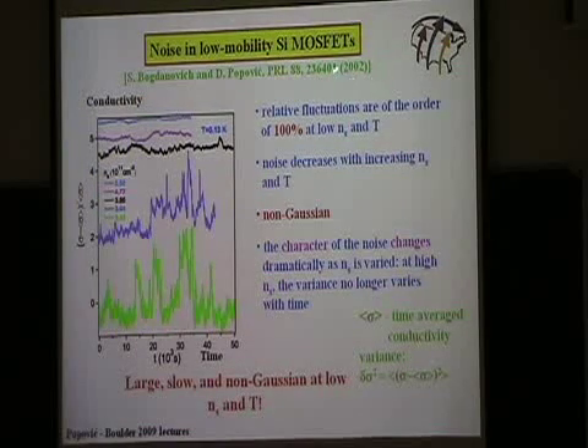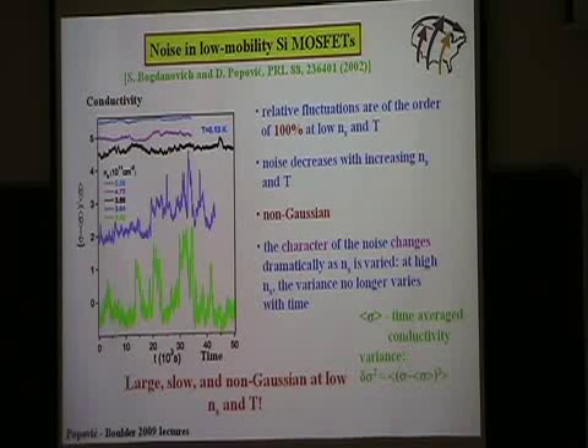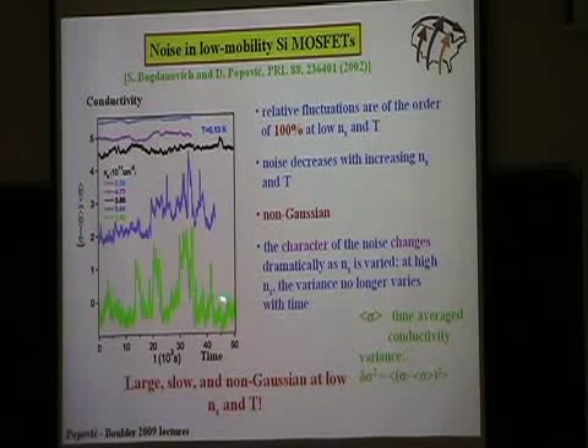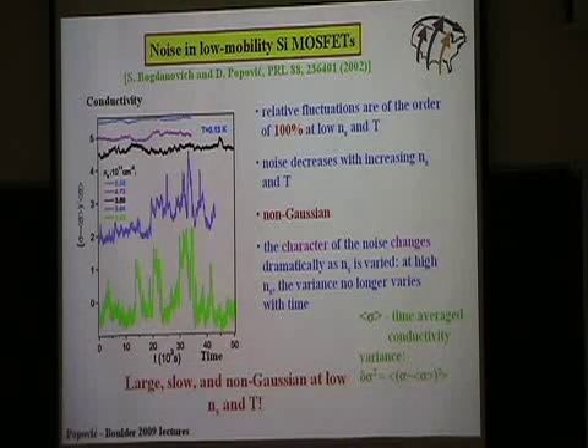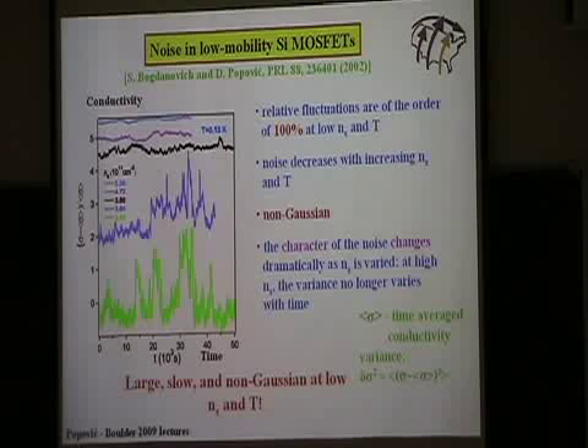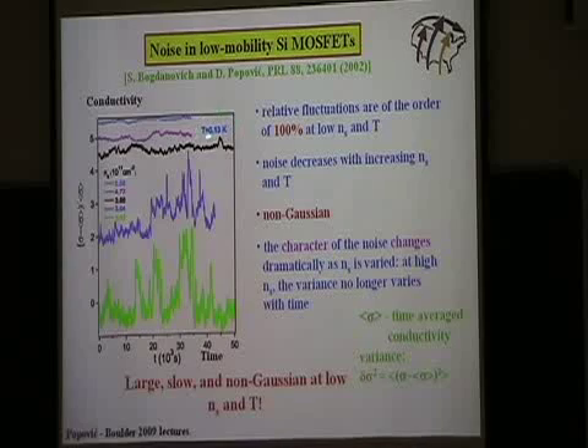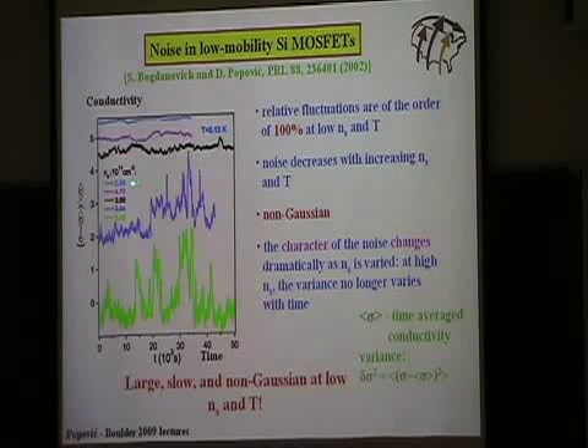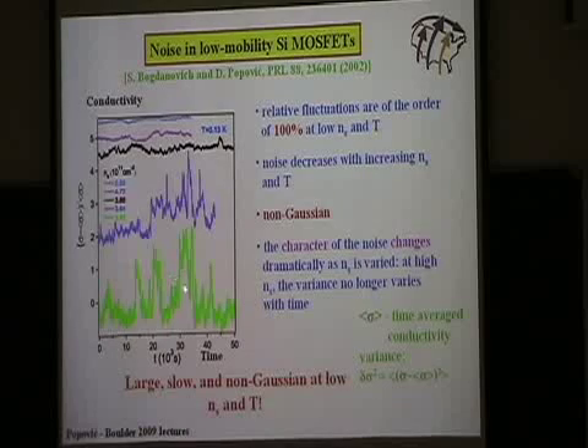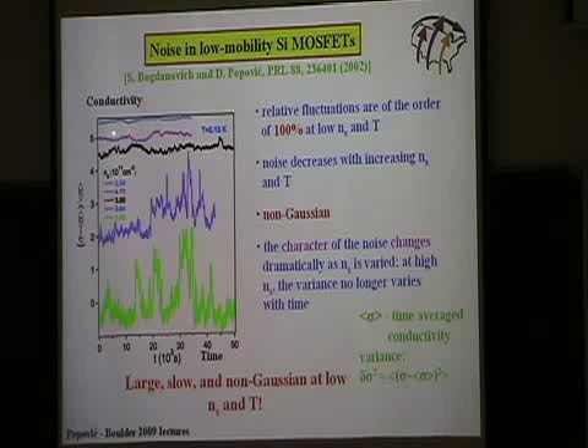You can see this was done a long time ago, before we did these relaxations. These are the relative fluctuations of conductivity, relative with respect to whatever average value you can get out of traces like this as a function of time. This was done for low mobility samples, that is samples that had a lot of disorder. These traces are taken at very low temperature, 0.13 Kelvin, and they correspond to different densities. And they're also shifted vertically for clarity, so we can look at the noise. So you can see that at the high densities, the noise is not that big, but when you go to low densities, it's huge.